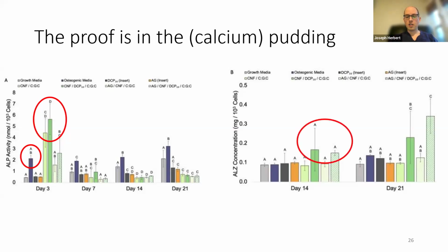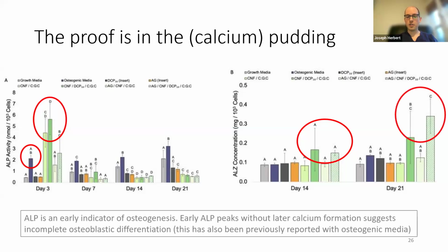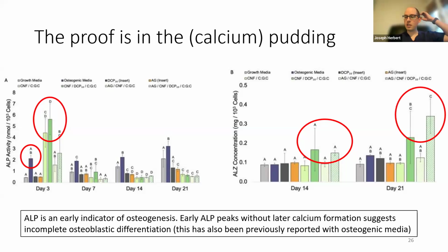And then looking at the right side, the ALZ concentration, which is another secondary marker of actual calcium formation, you can see with our graphed materials there on the right that are circled, a much higher concentration of ALZ. It's not really important to get into the weeds of these assays and how they work, but it's enough to say that ALP is an early indicator of osteogenesis. And so when you have an early ALP peak without later calcium formation, that suggests an incomplete osteoblastic differentiation.